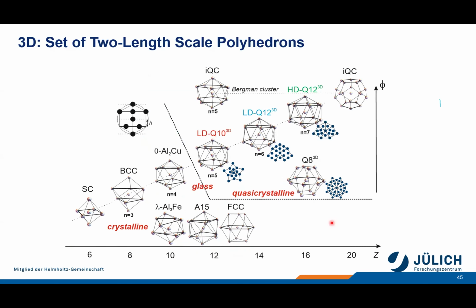So this was 2D. Now the interesting thing is the 3D arrangement. I told you about these special geometries here, which are the typical 3D packings for quasicrystals. So this would be the low density Q10 phase with the pentagon here and the pentagon here, meaning the central particle, and this theme of having a central particle surrounded by a shell of nearest neighbors is typical for quasicrystal packing. So this is the central particle surrounded by 5+5 tile, and this altogether gives a special kind of polyhedron,